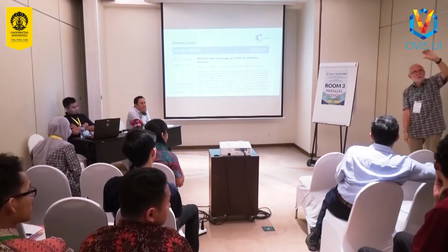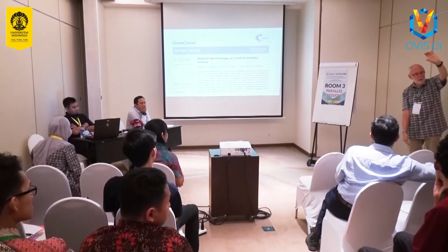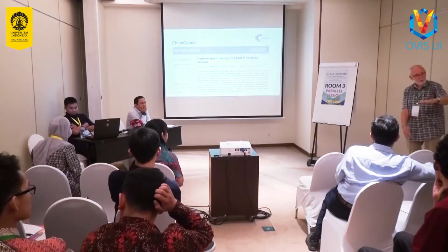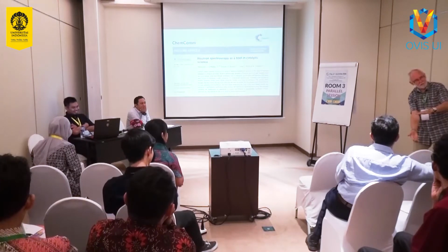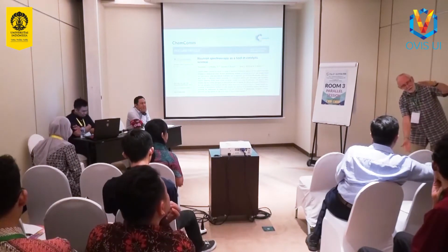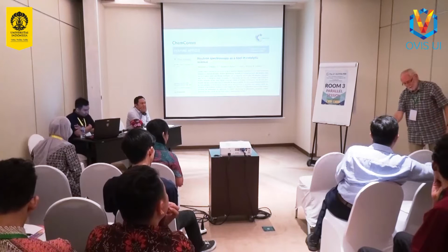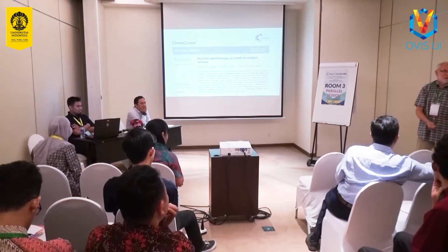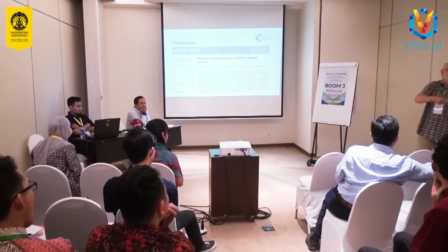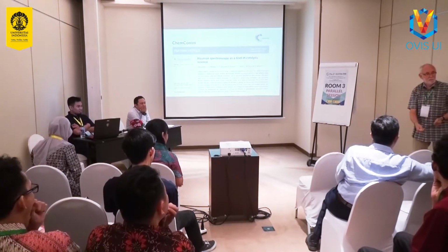Methanol comes in the top. Initially, it's the first part of the bed that is active, and then the reaction front gradually moves down through the bed. As this catalyst deactivates, further down it's still active. And eventually, the whole bed is deactivated, and then it stops making gasoline. At which point, they take it offline, they flow oxygen through it, regenerate it, and then they start it again.